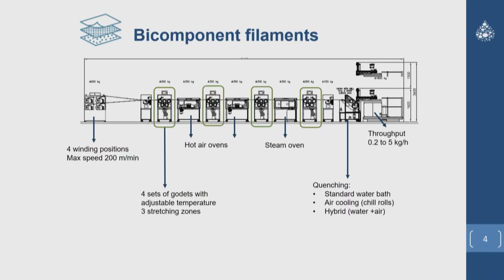For those of you who are not really familiar with filament extrusion, the line goes from right to left. At the right side you have the extruders. Here we have our high melting and low melting PLA grades in our extruders. They go through a die to get the nice core sheet structure. And then we start the production of the filaments. They go through a water bath to cool the material. And then we go over those different rolls to stretch the material. By stretching it, the polymer chains get aligned. And that gives the reinforcement and the strength of our filaments that we need in the composites.